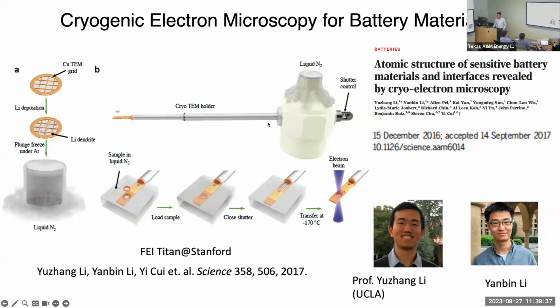This is a cold finger. We put liquid nitrogen right here, so we continuously freeze the sample close to liquid nitrogen temperature. Then we image under electron beam. Liquid nitrogen stabilizes your sample. That's one important one. The second one is, leveraging what structural biology has developed, the direct